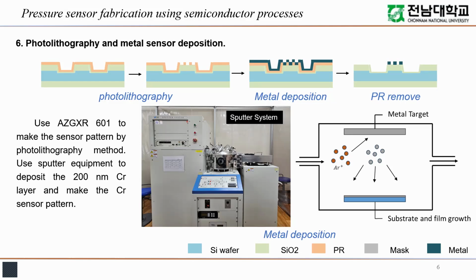This time we are going to use the sputter method to deposit the chromium as the sensor layer. And here just shows the equipment and the principle of the sputter deposition. We use argon ions to bombard the chromium metal target. Then the chromium atoms fall down onto the substrate and the film will be grown. Our expected thickness is a 200 nanometers chromium layer.